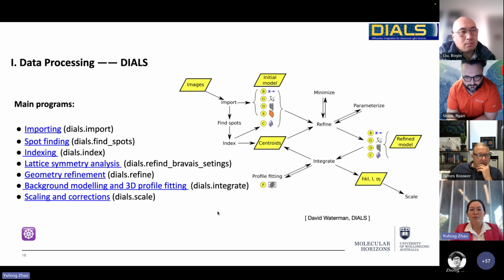So here's the flow chart of DIALS. It looks quite similar to all the other software, like the classic X-ray diffraction software XDS. Start from importing the data and find strong reflection spots, indexing, get the geometry, refine the geometry, integrate all the reflections, and scaling the data, then export for phasing and structure solving.